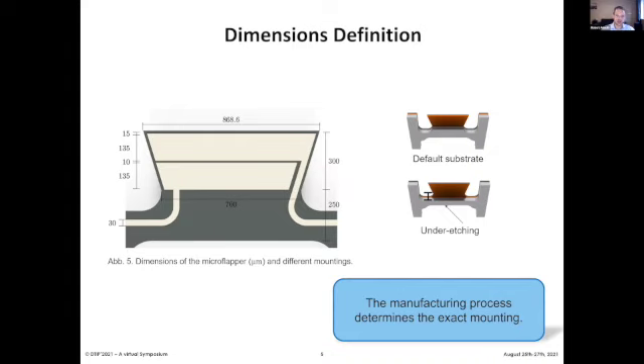However, when we look at the dynamic behavior on the next slides, we have to consider some manufacturing tolerances. During the manufacturing process, for example, under etching, which is a common issue, could occur and increase the length of the flexible part, which has therefore a strong influence onto the dynamic behavior. And this has to be considered when we want to determine an electrical signal for the excitation, since the operating point, I will show later, is really sensitive, and we have to account for such deviations from the ideal model we want to manufacture, or ideal device.